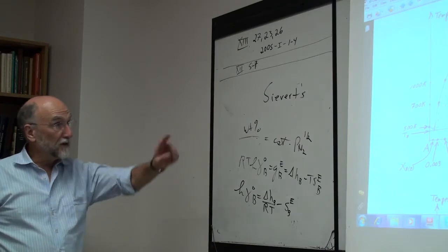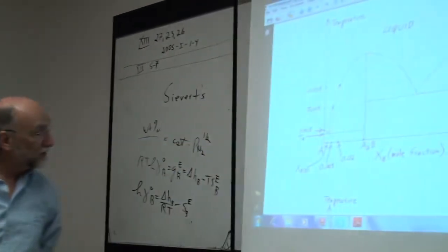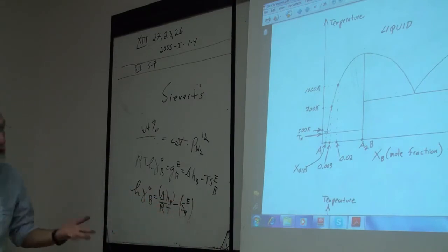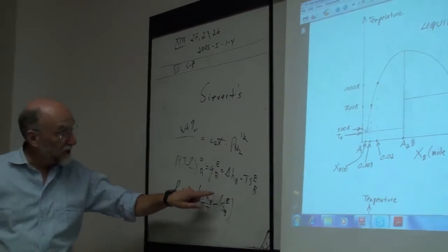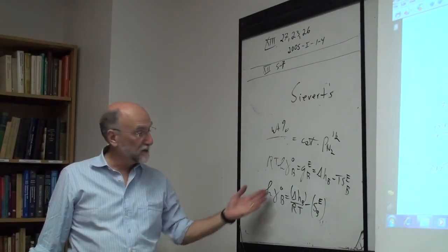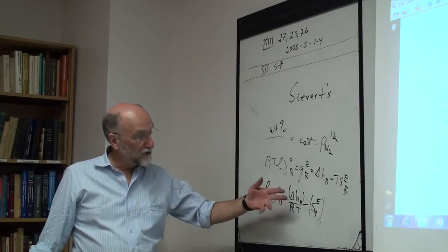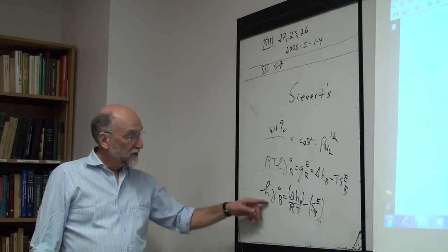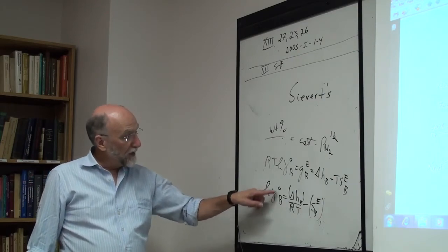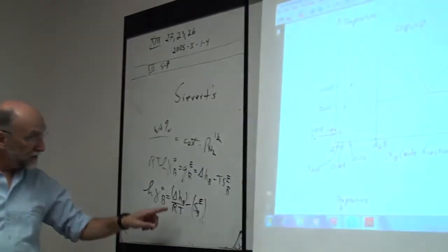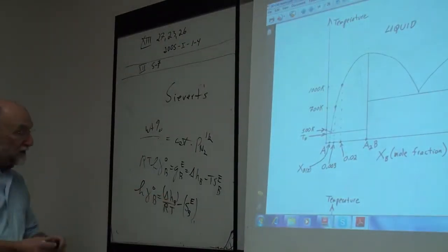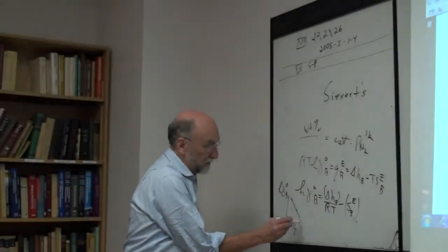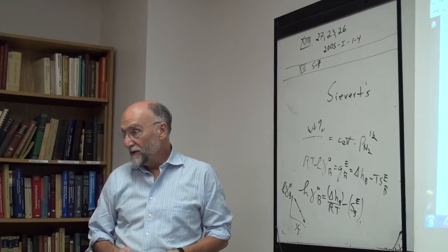Now, suppose it has been measured at 2 temperatures. That permits me to get delta H and S excess, which I assume are independent of temperature. That's a fairly good assumption, not perfect, of course, but pretty close. Usually we assume the excess heat capacity is 0, so the heat and excess entropy are independent of temperature. So if you've measured log gamma B at 2 different temperatures, that permits you to do a linear extrapolation. Basically, I'm just plotting log gamma Henry of B versus 1 over T, and I've got 2 points, so I'm extrapolating that linearly to a third point.